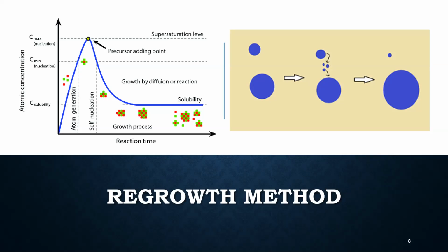where, as you can see on the right picture, Ostwald ripening, large particles obtain atoms from smaller particles that are dissolving. These two stages rely on seed concentration added in the solution. At high concentration, during focusing stage, smaller nanoparticles grow more rapidly than the bigger ones. When the seed concentration is depleted, smaller nanoparticles start to give atoms to larger nanoparticles and start to dissolve, which essentially widens the size distribution.